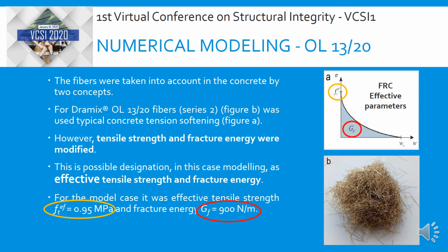The fibers were taken into account in the concrete by two concepts. For Dramix OL 13/20 fibers, series 2, figure B, typical concrete tensile softening, figure A, was used. However, tensile strength and fracture energy were modified. In this case, the modeling designation is effective tensile strength and fracture energy. For the model case, the effective tensile strength was 0.95 and the fracture energy 900.